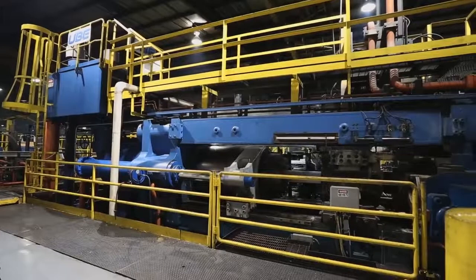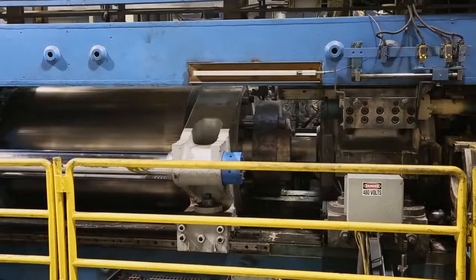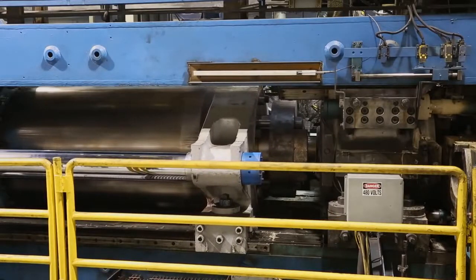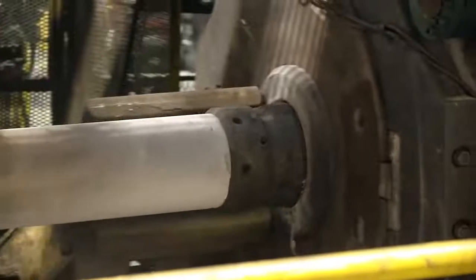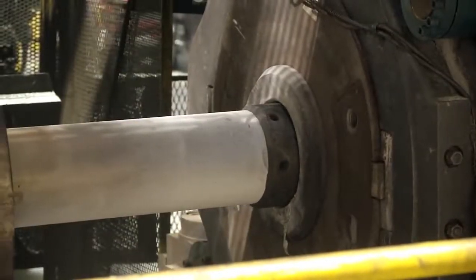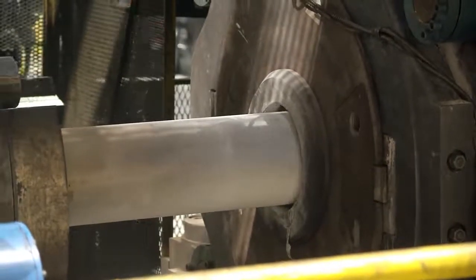There are two distinct aluminum extrusion methods. Most common is the direct extrusion method, where the material is pushed by the ram through the container and material exits through an opening in the stationary die. With the direct extrusion process, the center of the billet flows faster than the metal at the perimeter. That is because of the tremendous friction at the container walls.